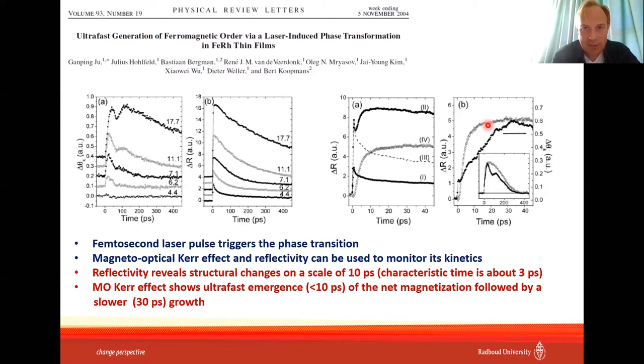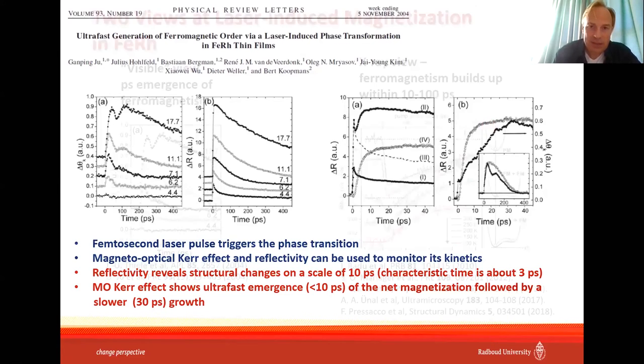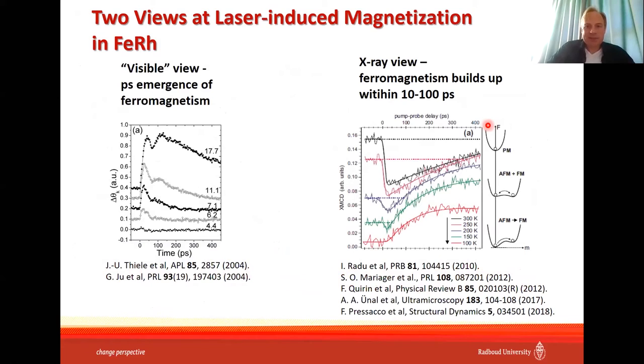We had in 2004, and what happened further? Actually, it is very interesting because follow-up studies can be divided into two groups. You could see here in the experiments, like I showed right now, that when you pump iron rhodium with a short laser pulse, you first see an ultrafast increase of the magneto-optical Kerr effect, which is interpreted as an ultrafast increase of the magnetization, and consequently, it implies that there is a very fast transition from antiferromagnetic to ferromagnetic state.